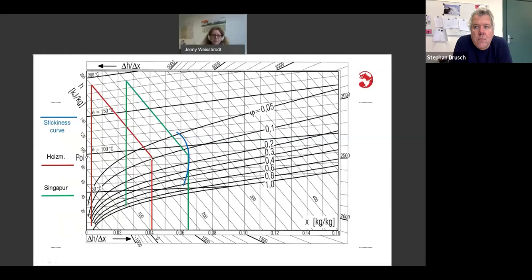I stopped my virtual drying process at 90 degrees C outlet air temperature, and you see that a lot of water has been taken up by the drying air. We end up at roughly 42 grams water per kilogram air at the end of our process here.